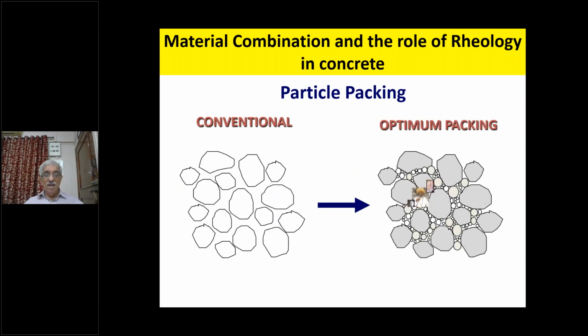Just to give you a very simple and practical thing, you see material combination and the role of rheology in concrete. Conventionally, we were using only cement. So the gaps between the cement particles used to be filled with water. And later on, the water would disappear, causing shrinkage and cracks. Now, in high performance concrete, we are very sensibly using the fine and ultra fine materials like fly ash, slag, ultra fine fly ash, ultra fine slag, silica fume, etc., and